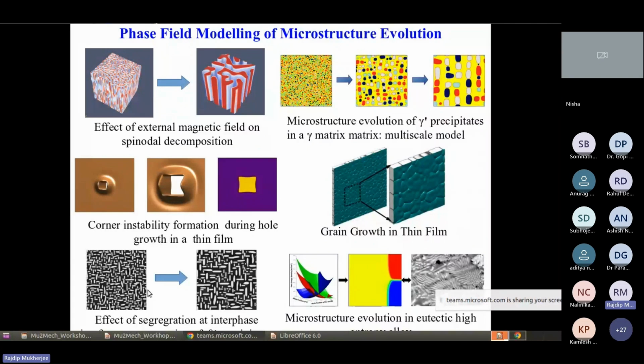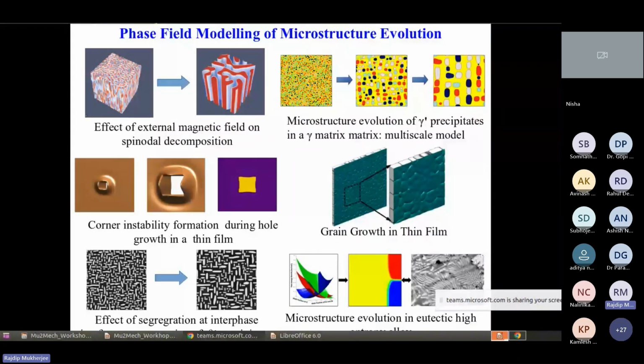There are, say, titanium alloys which are used for space applications, right? Which are very expensive. We cannot use them in normal aircraft or automobile applications. They're like titanium, titanium 6 aluminum 4 vanadium, this kind of alloys. But they are very lightweight and high strength alloys. But these are also precipitation hardened alloys, where alpha HCP phase is embedded in a BCC matrix, right? So these precipitation hardened alloys are very important. They form because of phase separation, and this Mu2Mech software targets one of such alloys. You can actually simulate defined alloy systems which are precipitation hardened alloys, right?